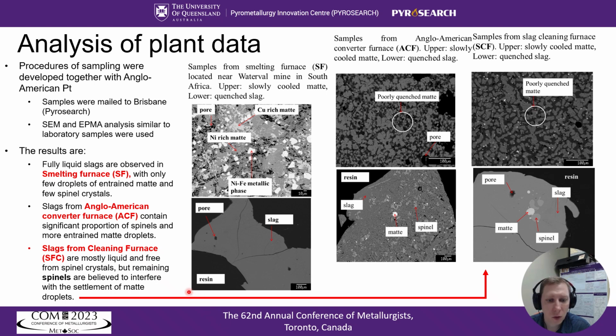In the case of smelting furnace, the slags are fully liquid, with very few droplets of matte and almost no spinel crystals. The slags from the converter furnace contain significant amount of spinel crystals and more matte droplets. The slags from the cleaning furnace were mostly free from spinels, but the remaining crystals were often associated with matte droplets, and we concluded that they may interfere with the settlement of the remaining matte droplets.